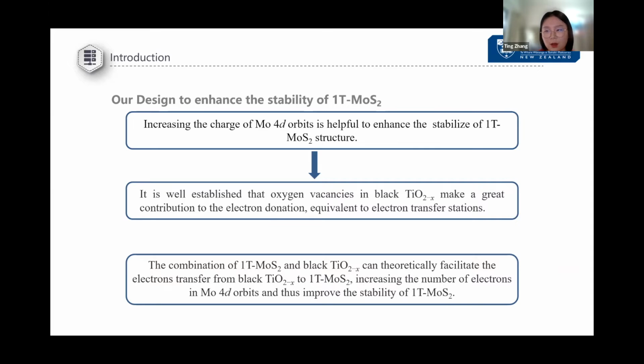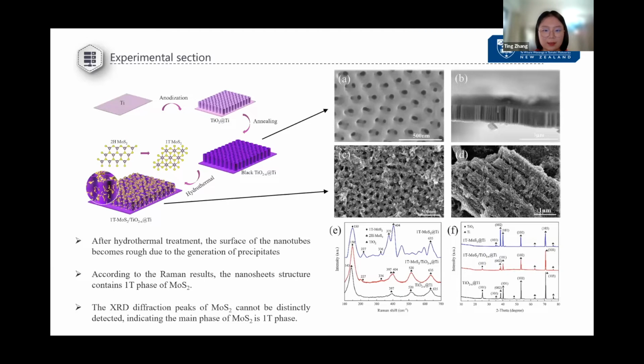So we are thinking, why not combine our black titanium dioxide with the 1T-MoS2 phase? Maybe the black titanium dioxide can donate electrons to the 1T-MoS2 phase and make it stable. So we use the anodization and annealing method to produce black titanium dioxide nanotube arrays as a substrate. And we use the hydrothermal reaction to decorate MoS2 nanosheets on the surface of the nanotube array substrate and both in the